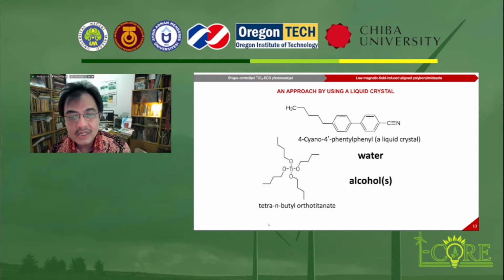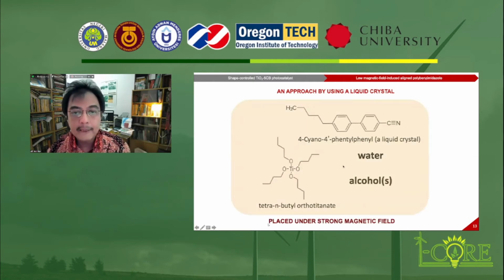The synthesis process is very simple, namely placing 4-cyano-4'-pentylbiphenyl, this is a liquid crystal, water, alcohol, and tetrabutyl orthotitanate in a homemade magnet apparatus. The composition of the precursors is varied to get the best result. This is a very simple procedure, and this is the result obtained.